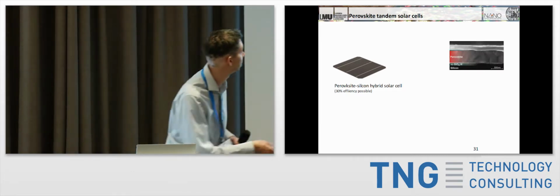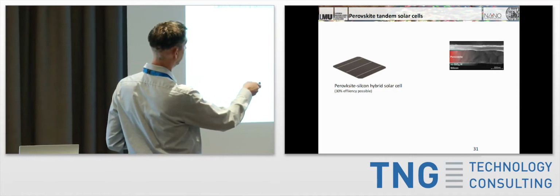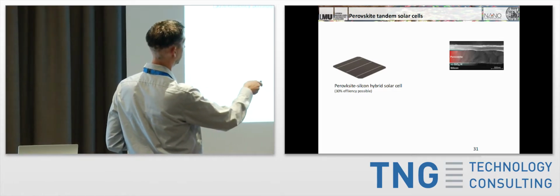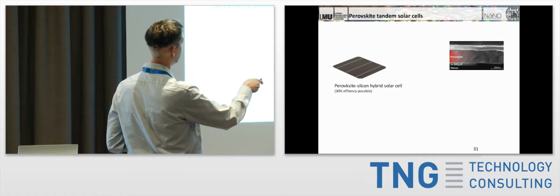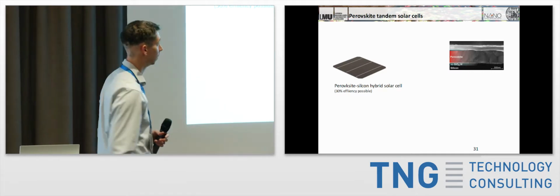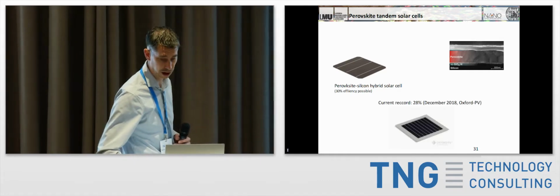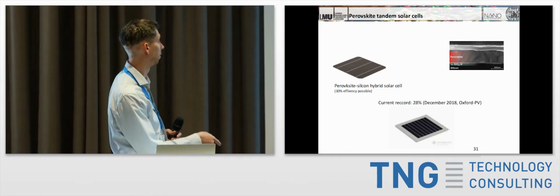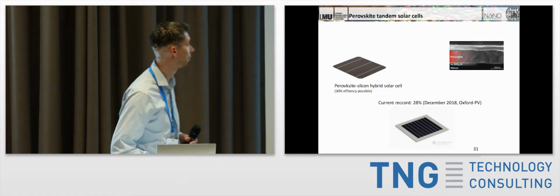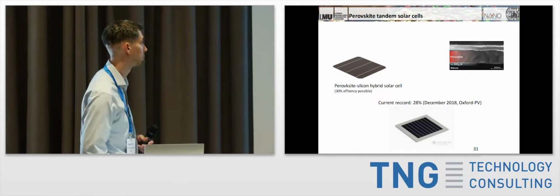Cross-section again of this cell, so this is only the top of the silicon layer, then you have a little layer in between to passivate it and also for extracting charges, and then the perovskite sitting on top of it, and then a transparent conductive electrode sitting on the top. And this is what one of their cells looks like, and they currently hold the record for a tandem solar cell, which is at 28%.